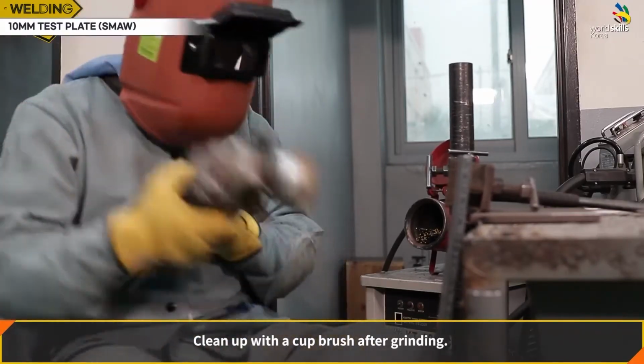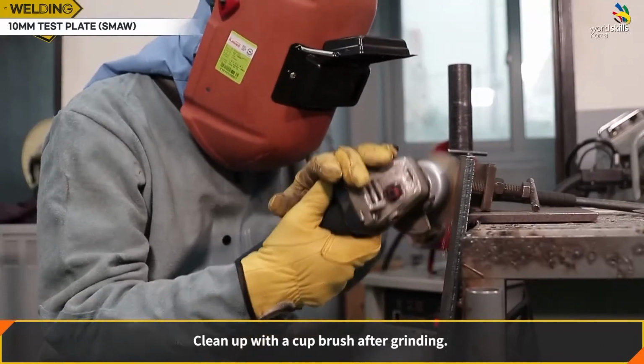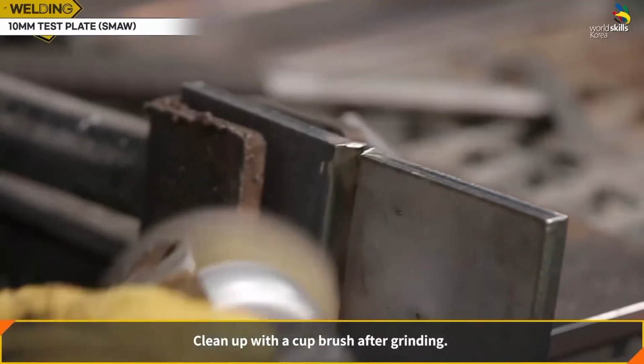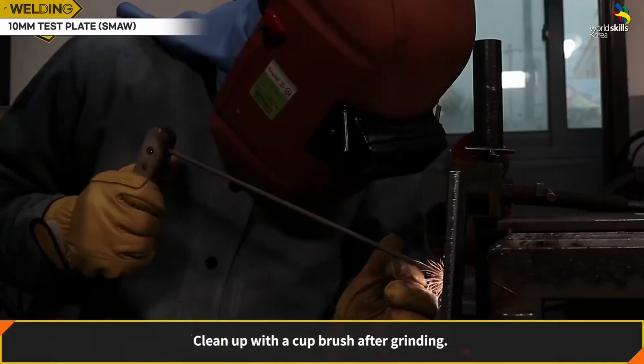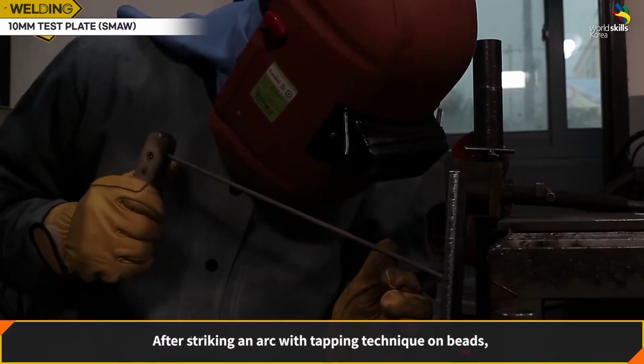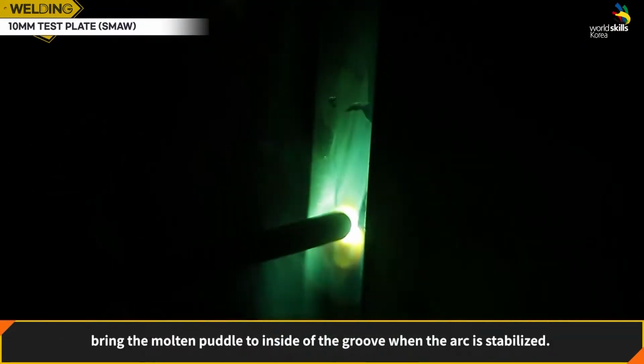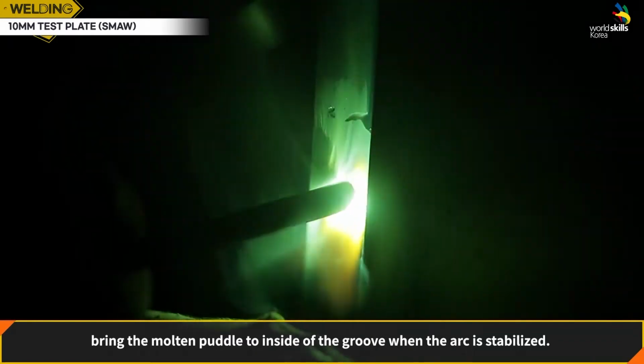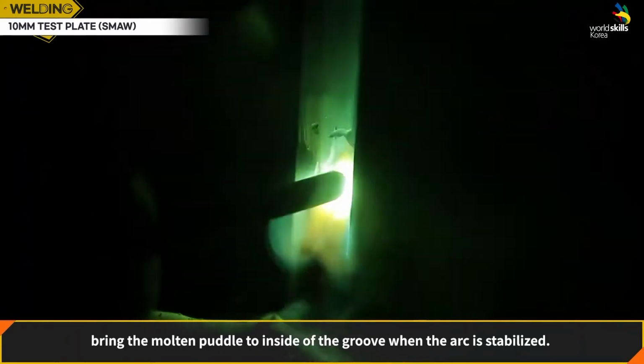Clean up with a cup brush after grinding. After striking an arc with the tapping technique on beads, bring the molten puddle to the inside of the groove when the arc is stabilized.